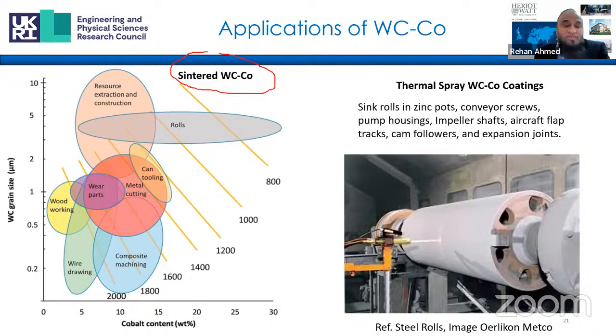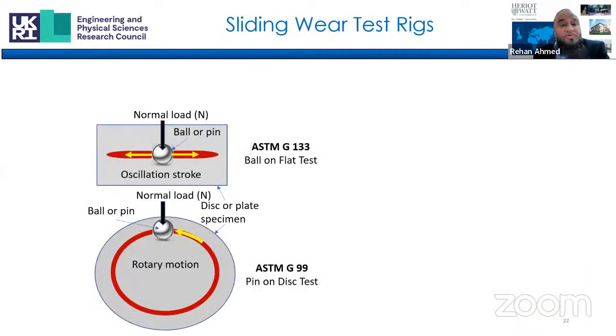So the wear performance of tungsten carbide cobalt in both sintered or coated form is dependent on carbide size, cobalt content, amongst other microstructural and tribological considerations. So predicting the sliding wear performance of coatings requires us to understand the complex interdependencies of the wear mechanism. And before we embark on full-scale testing of coated components, the cost of development can be significantly reduced using the ASTM test procedures. And in sliding context, there are three important tests, which are either used independently or in combination to understand the wear mechanisms and predict the wear rate.